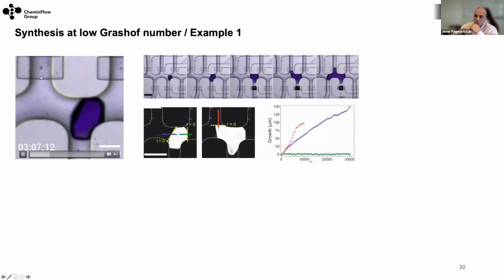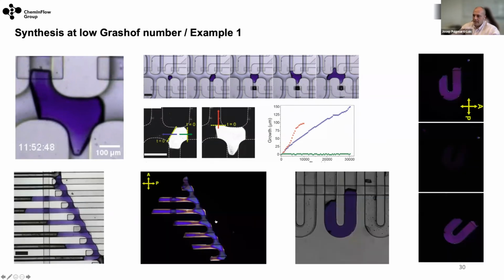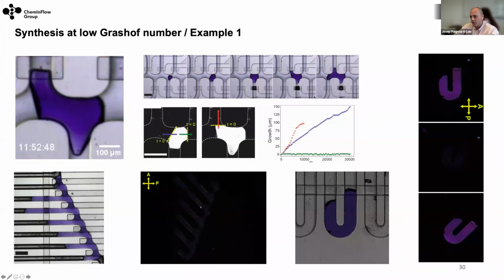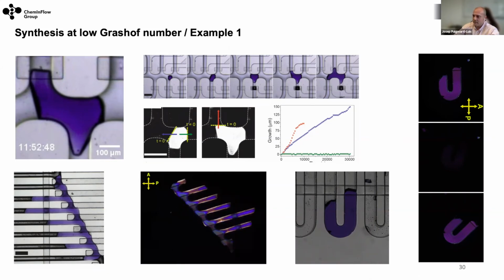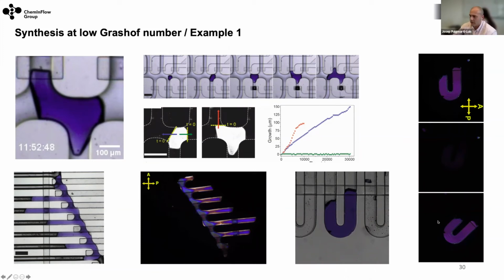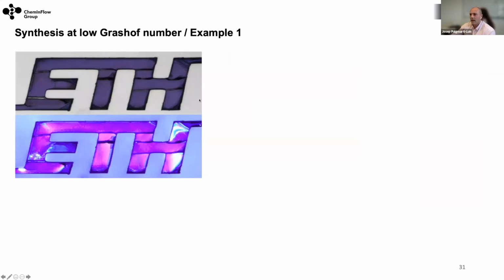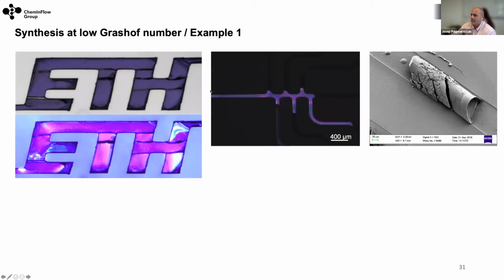And this is something that we try to do with this microfluidic device. As soon as we add new fresh solution, the growth gets accelerated, and this is what you see there. So with that, by changing the chip design, we could achieve single crystals with very intricate morphologies. You see there, it's also a single crystal. It has this U shape, and then we also made crystals that in this case were not single crystals, but if you look at this here, this is a millimeter long. So we could control very nicely not only the length of the single crystal, but also the shape.